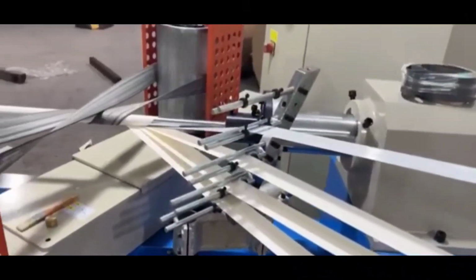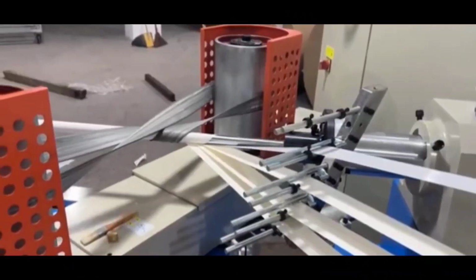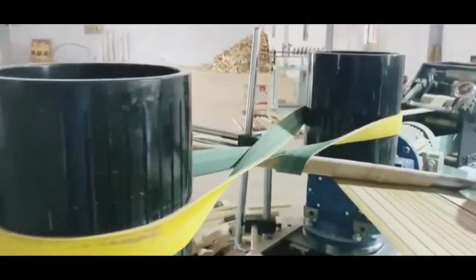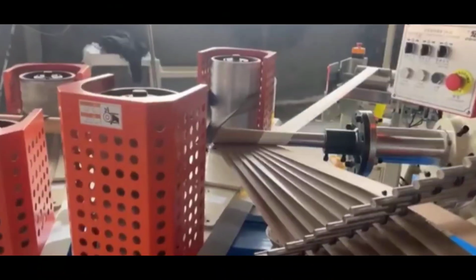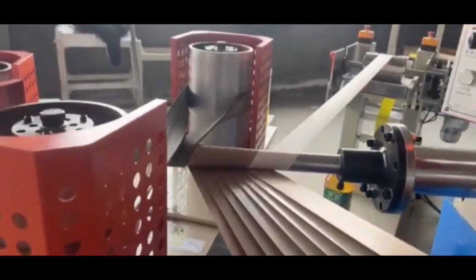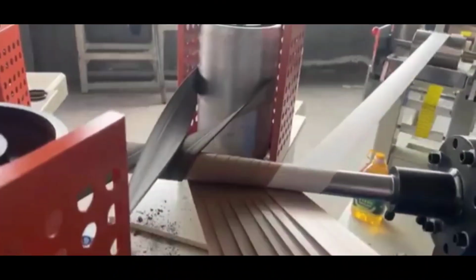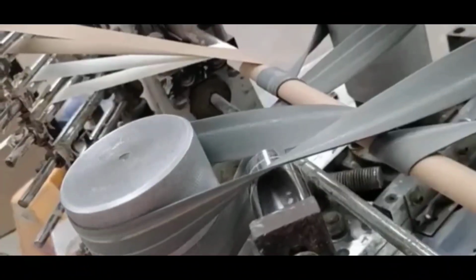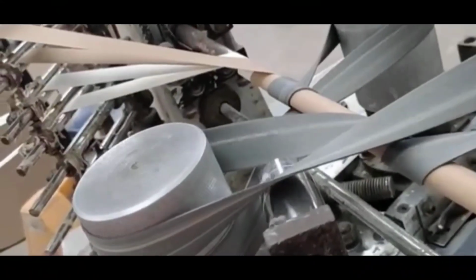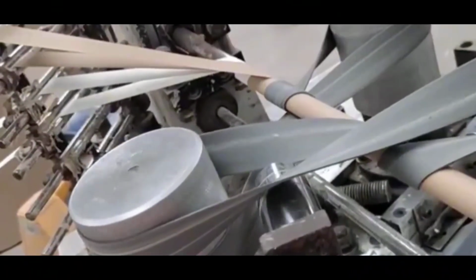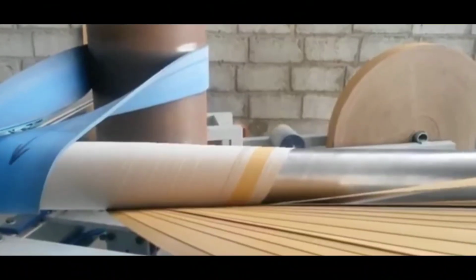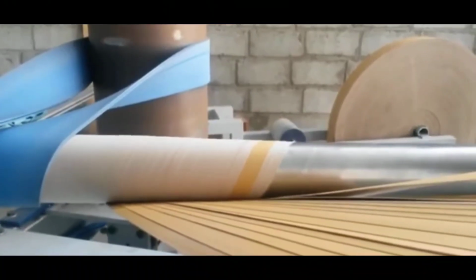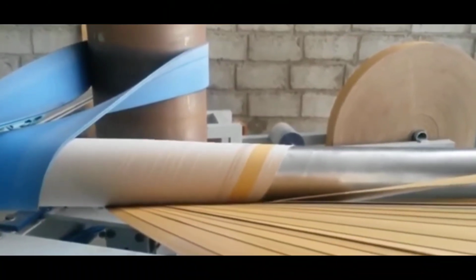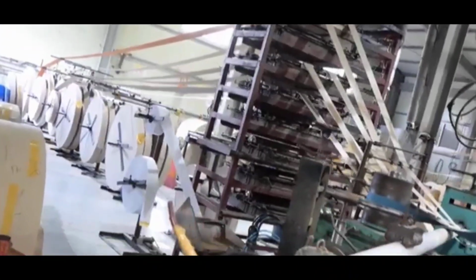Next, the core winding machine feeds the coated strips onto a steel mandrel set at an angle between 30 and 45 degrees. As the layers spiral, pressure rollers apply roughly 150 psi, compressing each layer uniformly to create a dense, gap-free structure. A servo sensor synchronizes mandrel rotation and paper feed speed, ensuring the helical pattern remains perfectly aligned.